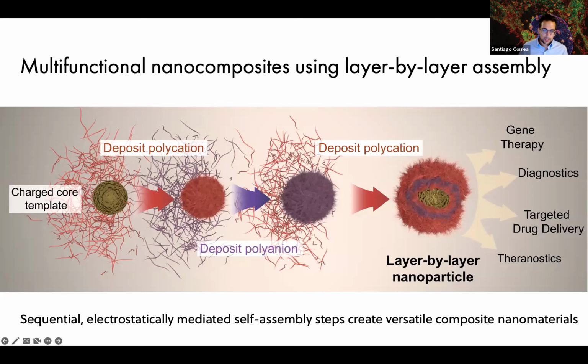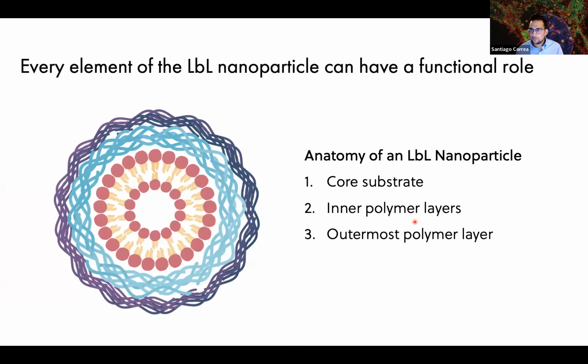I mentioned before this nanocomposite, which I refer to as a layer-by-layer nanomaterial. These are materials that use a process called the layer-by-layer assembly approach, and you can use this to build composite materials either in 2D or in 3D, depending on the kind of substrate that you're working with. This image schematizes this approach. It's essentially the sequential deposition of different polymers onto a substrate. In this case, I'm showing a gold nanoparticle, and we're leveraging electrostatic interactions in this particular cartoon to build up multiple layers of different polymers. By incorporating these different functional materials into a single nanoparticle, we can develop platform technologies that can carry out complex tasks downstream that have useful implications for biomedical applications. So that's layer by layer at a high level.